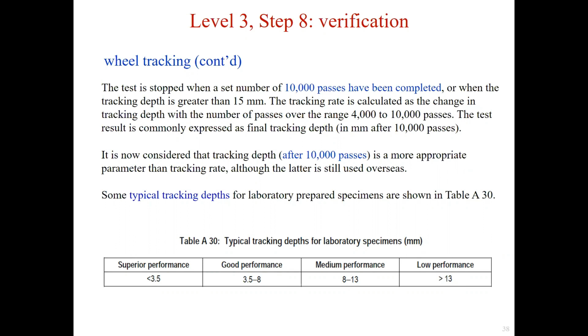Although the tracking rate is commonly used overseas, it is now considered. The tracking depth after 10,000 passes is a more appropriate parameter to indicate asphalt performance. Some typical tracking depths for laboratory prepared asphalt samples are shown in the table below. So if the tracking depth is 3 millimeters, it indicates superior performance. Otherwise, 14 millimeters indicates low performance.